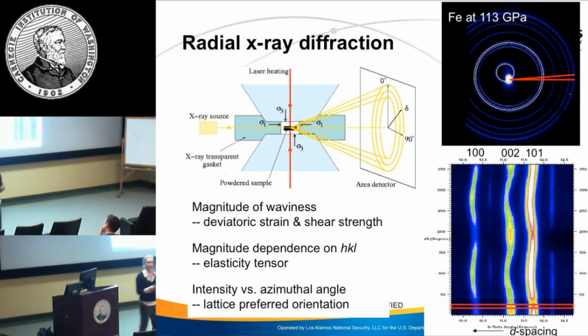Okay, this is going to set up a view of our Debye-Scherrer cones at their most non-hydrostatic, but with access to the maximum waviness. If you were to unroll these circles or ellipses, you'll see some distribution in d-spacing of the different crystalline planes or Bragg peaks in your sample, in your HCP. Okay, so my idea was to apply this to shock compression.